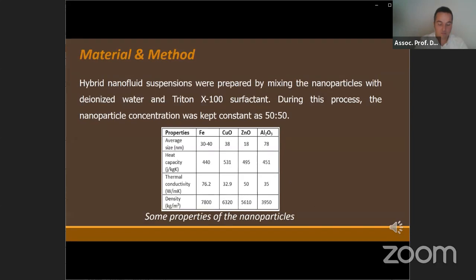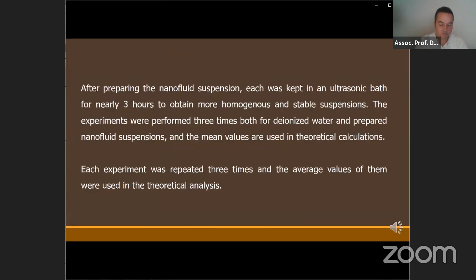Some properties of the nanoparticles used in the experiments can be seen in this table. Hybrid nanofluid suspensions were prepared by mixing the nanoparticles with deionized water and Triton X-100 surfactant. During this process, the nanoparticle concentration was kept constant at 50-50. After preparing the nanofluid suspension, each was kept in an ultrasonic bath for nearly 3 hours to obtain more homogeneous and stable nanofluid suspensions. Each experiment was performed 3 times, both for the deionized water and prepared nanofluid suspensions, and the average values were used in the theoretical calculations.